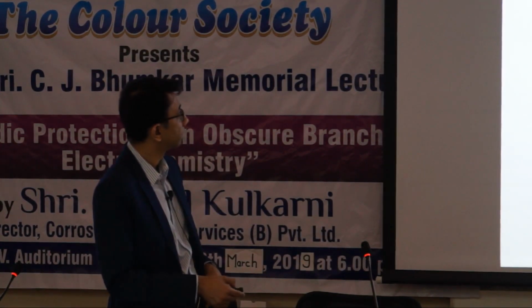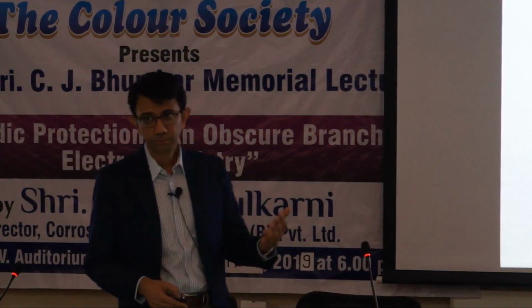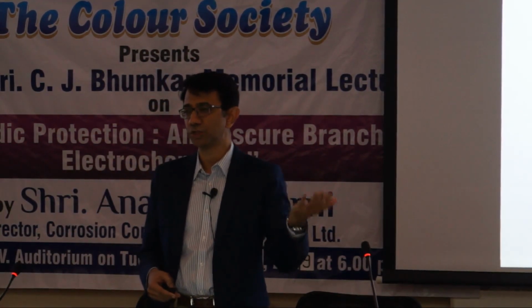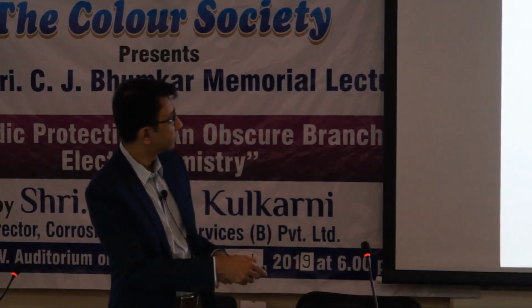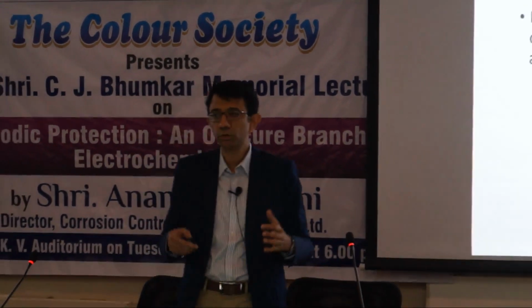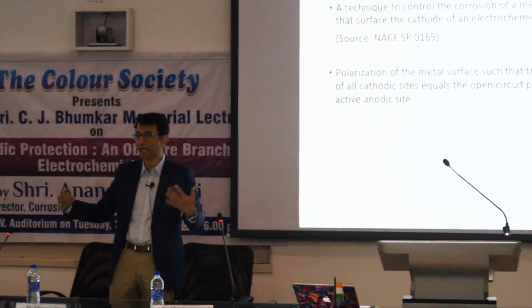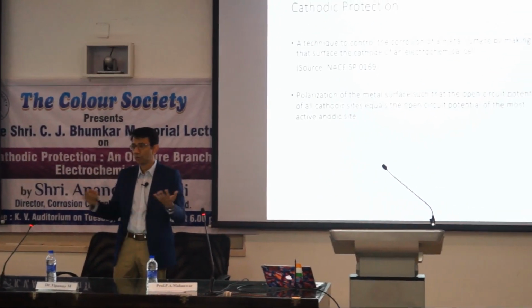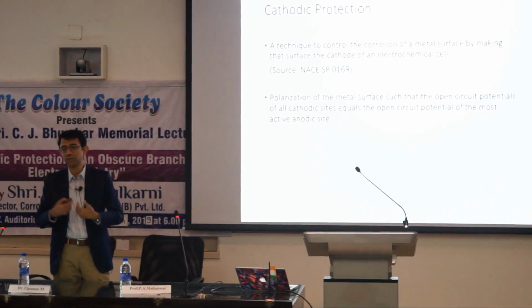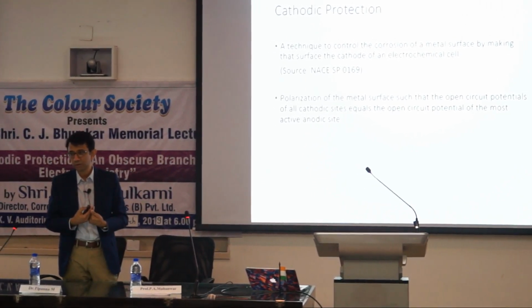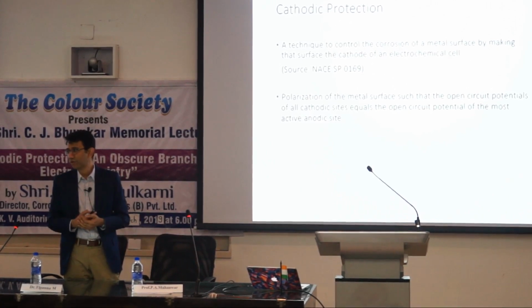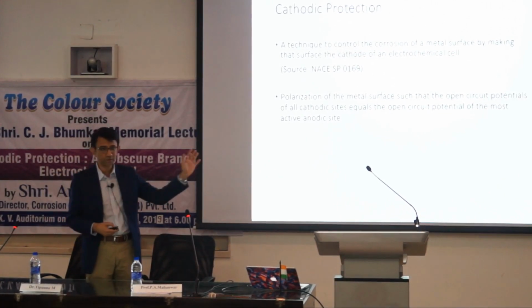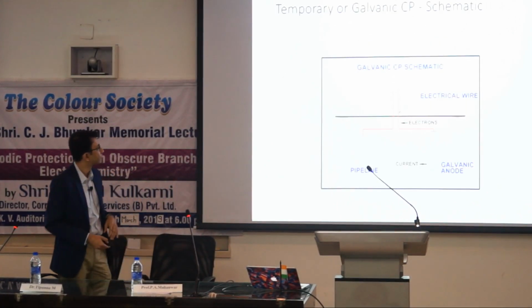polarization, if we polarize, meaning shift the potential of all the cathodic sites so that it equals the open circuit potential of the most active, electrochemically active anodic site. Well, obviously, if you have no potential difference between the cathodes and the anodes, then you don't have a cathode, nor do you have an anode. So then you have protection. And this is exactly what cathodic protection does.